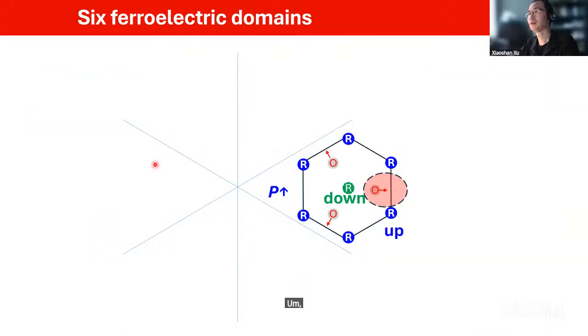And one thing I do want to mention has to do with symmetry. This is a hexagonal material, so you should have some kind of six-fold symmetry, right? One of them is in so-called domains. I showed you this kind of diagram, a top view. One down and five up, right? So that means we have more up than down. So polarization is up, okay?